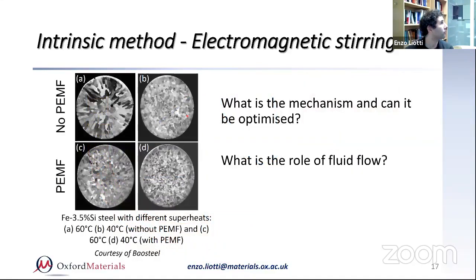This is an example of the effect of adding magnetic stirring to an iron or steel sample, and you can see with and without the PEMF in different conditions. So it is known that if you stir the sample, you enhance the formation of an equiaxed microstructure, but what is the mechanism and can it be optimized? What is the role of the fluid flow? Is it just mechanical breaking, or is there another mechanism? And can we exploit it more?